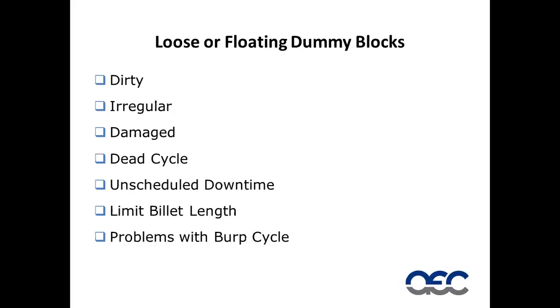We started out with a loose or floating dummy block prior to 1986, and I must admit I was in a country about 2 months ago where 95% of all the extruders still use loose or floating dummy blocks. The problem with these dummy blocks is, number one, most of them spend some time on the floor or in the pit and they're dirty. Most of them fall into that pit and they become irregular or damaged. They typically extend the dead cycle because we have to load them and unload them every cycle.